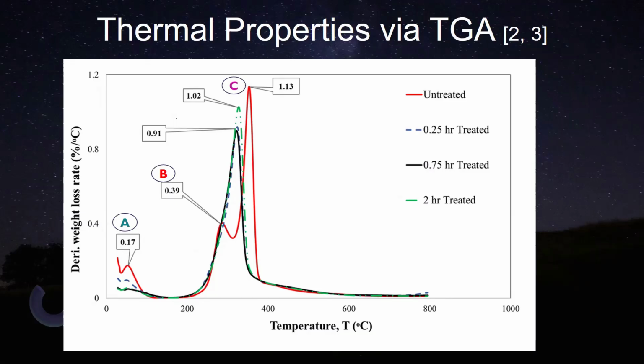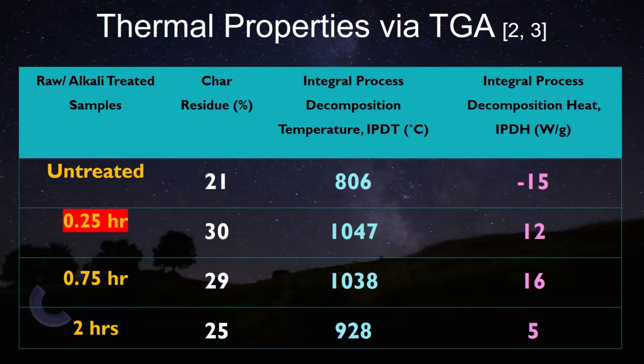And another interesting thing you can see is that when it is untreated, the maximum weight loss rate is higher. With the treatment, it actually reduced. So there is a connection between the weight loss rate and enhanced thermal property. We'll see that when we take that value into a table. I did not enclose all those values over here. The article has already been published, so those are cited over there.